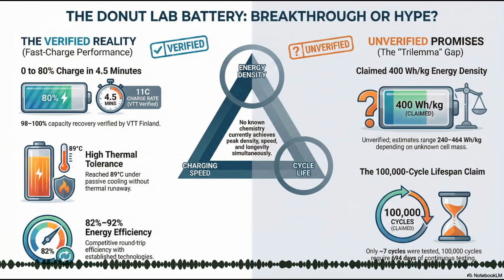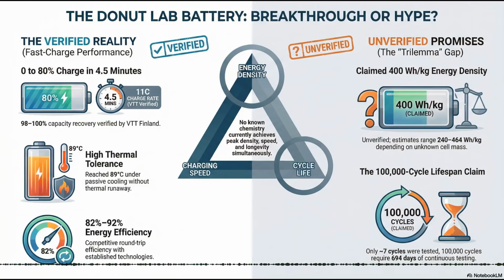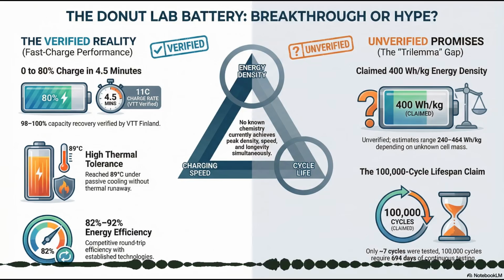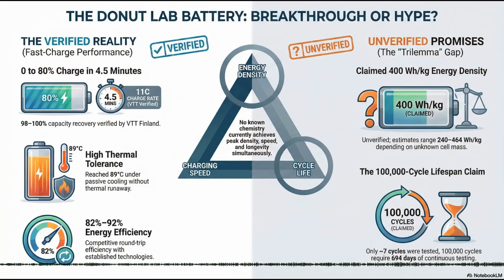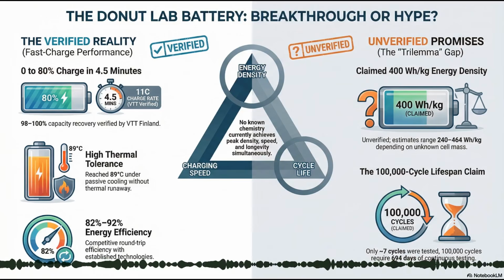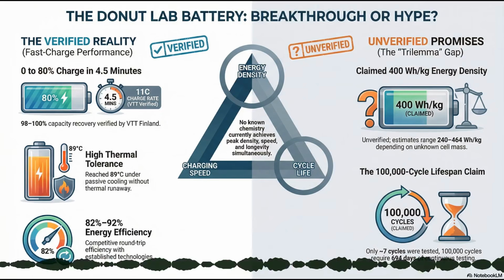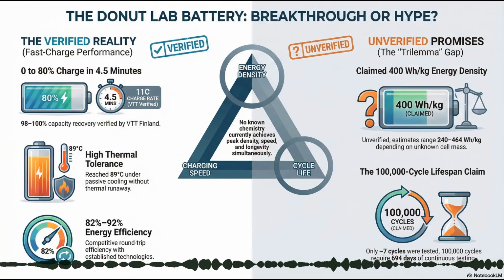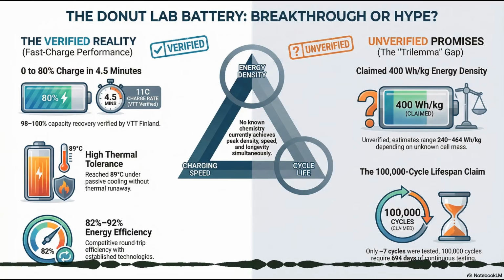Is there any battery chemistry on Earth that actually lasts 100,000 cycles? There is one that gets close. LTO, lithium titanate oxide. Toshiba makes them, the SCiB cells. They reliably last 20,000 to maybe 45,000 cycles. Why do they last so much longer than everything else? Because LTO is what we call a zero-strain material. The crystal lattice is a specific spinel structure. When lithium ions go in and out of that lattice, the unit cell dimension barely changes. It expands by maybe 0.2%. Yeah. It doesn't breathe. It's rock solid, mechanically stable forever.